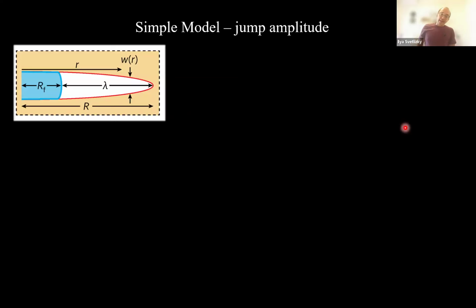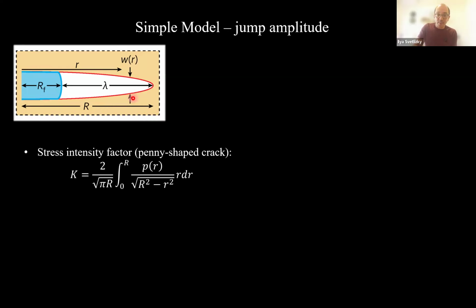Now what I want to do is take the same analogy and apply it to our fluid-driven crack. A couple of notations: the radius of the crack is R, the fluid front is denoted by RF, the lag is lambda, and the crack opening is W. So we can write the stress intensity factor for a penny-shaped crack. Let me stress that we are ignoring any transfer dynamics that I was pointing out earlier. So it's a pure circle, and it expands like a circle.